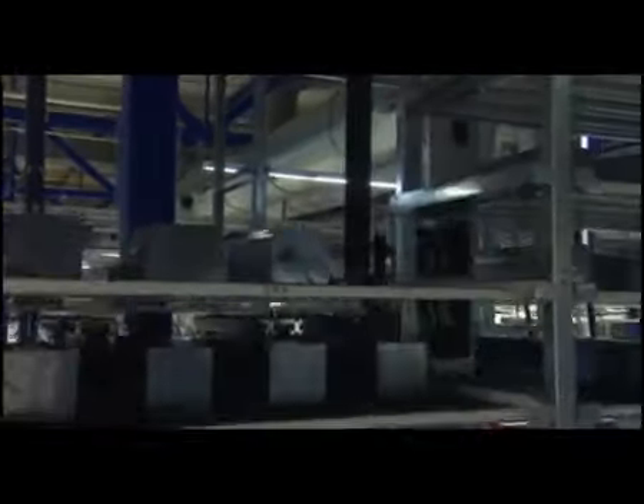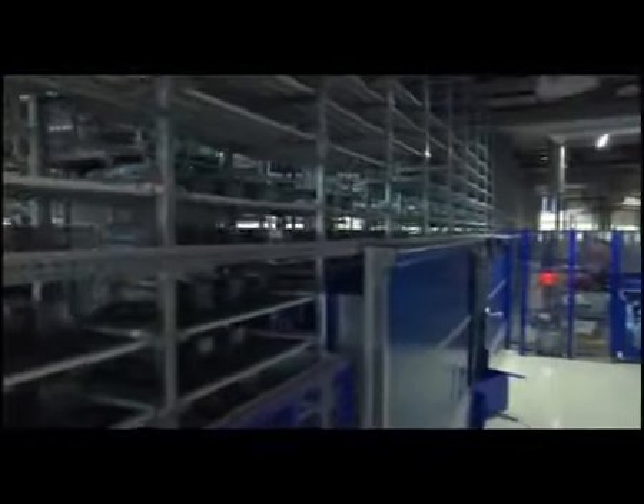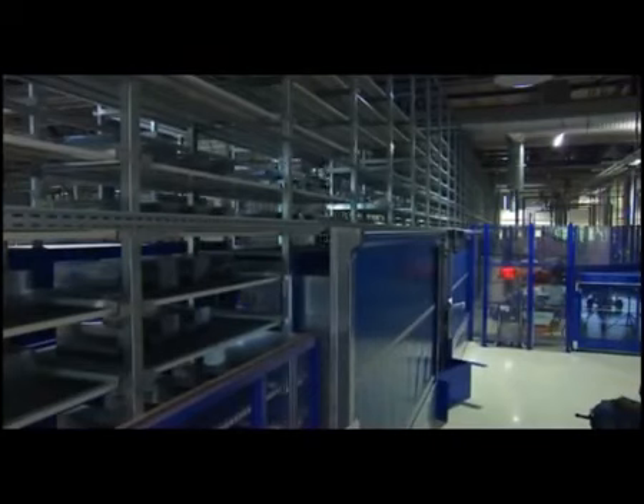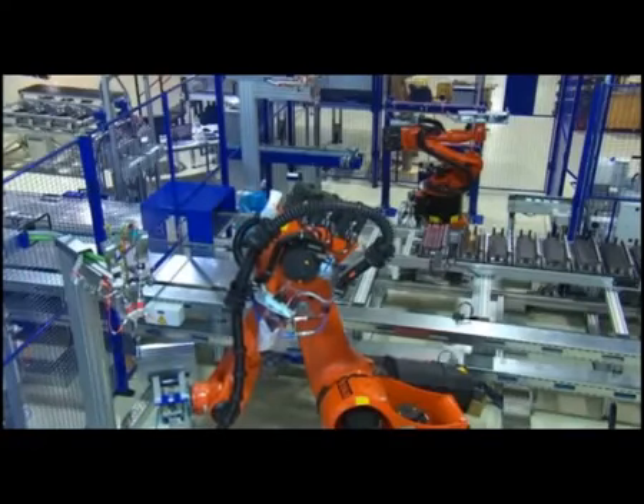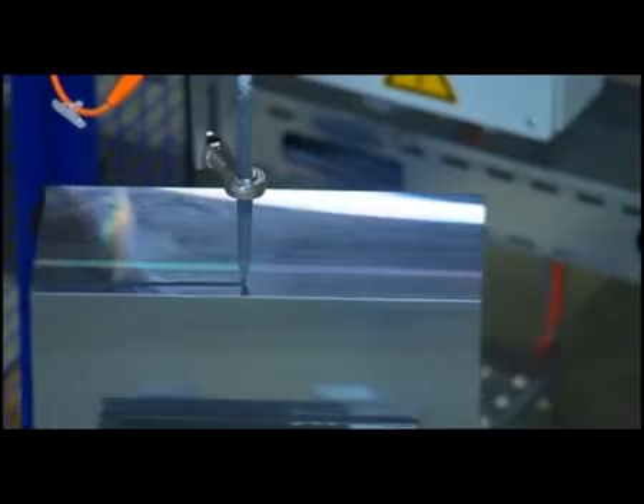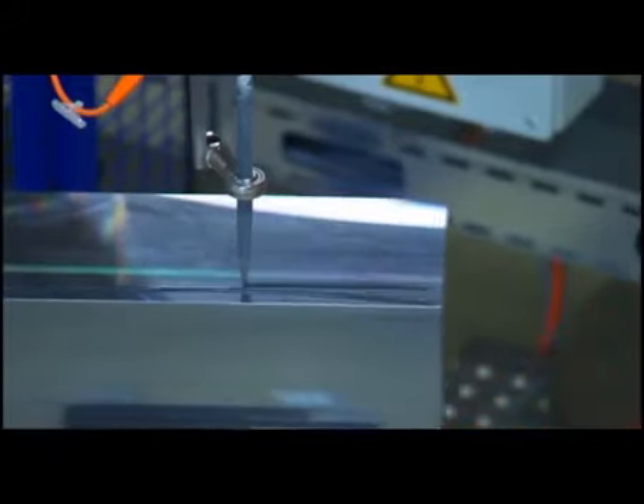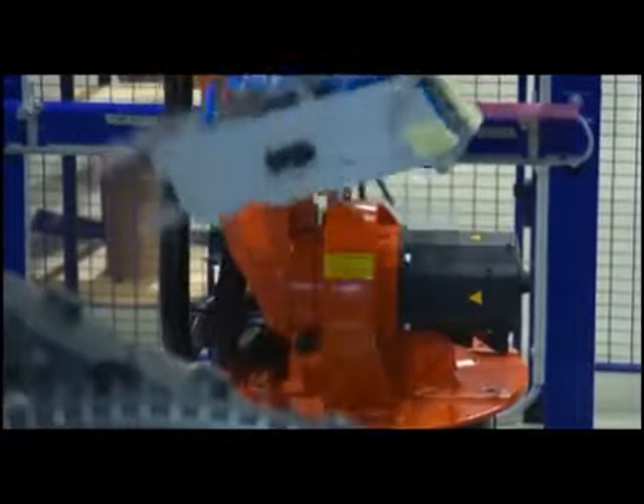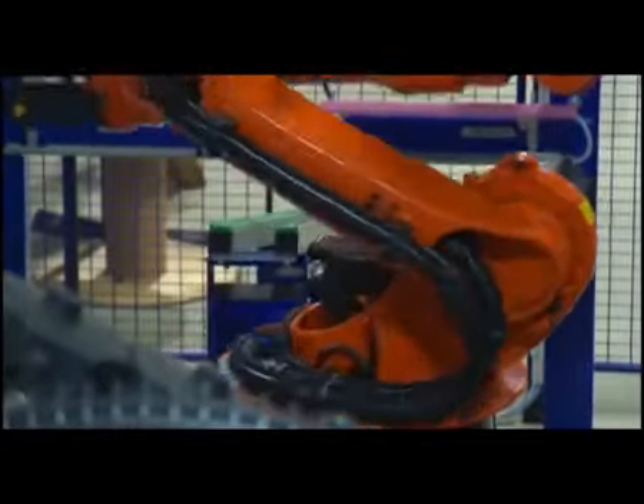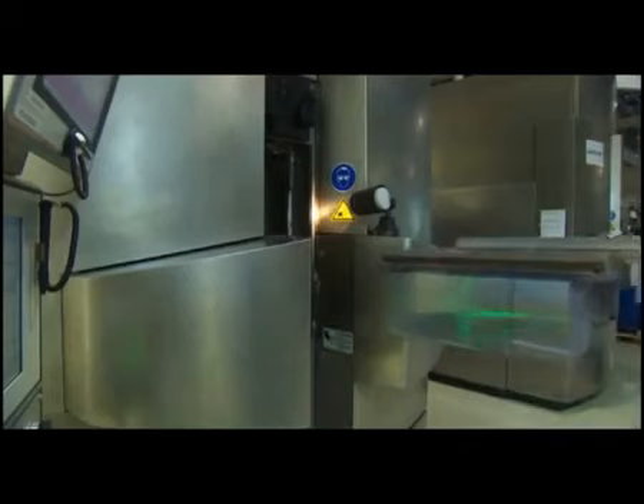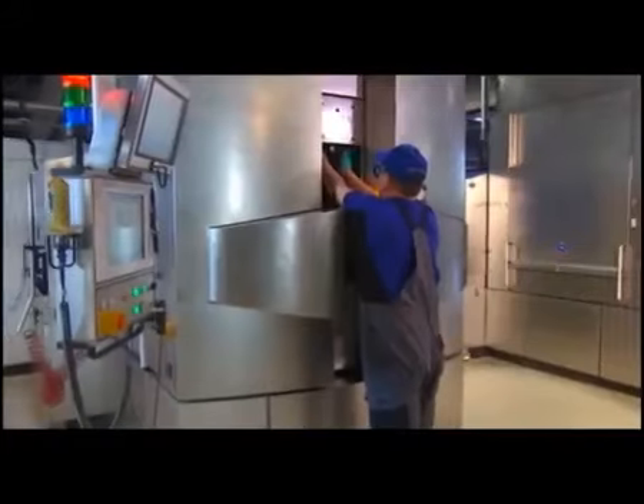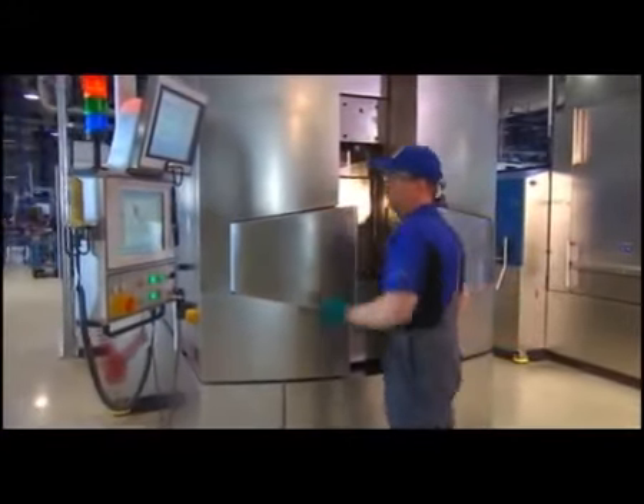Via the fully automatic shelving system, the pre-sorted silicon bricks are then transferred to the wafer fabrication stage. The bricks are bonded to both a glass plate and a carrier panel, a technology that has been developed and continually improved by Solarworld's experts. In the wire saw section, which comes right after the bonding center, another wire saw process is used to cut the bricks into thin discs, the so-called wafers.